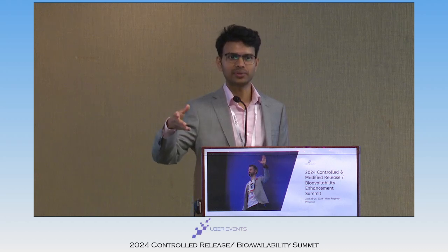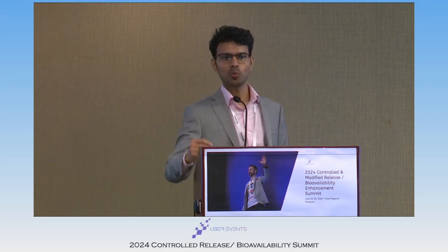The experiment that I was showing is unidirectional water uptake. But in an actual scenario, when you drop the tablet in the physiological media, it is surrounded by water throughout. So the water uptake is going to be multidirectional, and I'm sure it is also going to help, provided you have an adequate amount of MCC. On the last slide I showed that when you vary the concentration of MCC extragranularly from 5 to 20%, you need to find the inflection point at which you get the interconnectivity of MCC that helps drive water into the matrix. So yes, it may apply. Thank you.